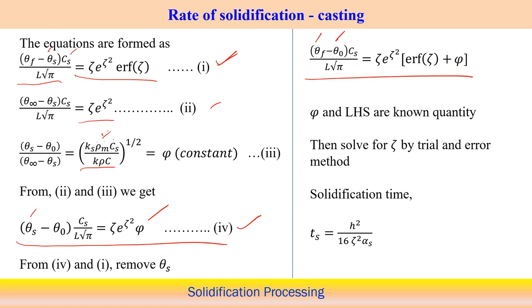So theta f and theta 0 are defined, the material properties are defined, and zeta is the unknown here. Phi is not really unknown, because phi can be calculated from here. Phi equals the square root of k s rho m c s divided by k into rho into c. So you can easily find the phi value, because all are material properties. The left hand side is also a known quantity, because theta f, the freezing temperature, and the initial temperature are known, and the others are material properties. So the only unknown is zeta.